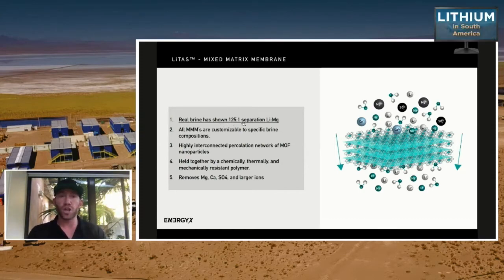The separation that we've shown on real brine from South America is 125-to-1 lithium over magnesium. So 125 lithium ions pass through for every magnesium. We are able to customize our mixed matrix membranes to specific brine compositions. Some of the factors include the type of metal organic framework we put in, the weight percentage of metal organic framework, the porosity of the polymer, and the adhesion factor. These mixed matrix membranes are highly interconnected percolation networks of metal organic framework nanoparticles. They're held together by a chemically, thermally, and mechanically resistant polymer.